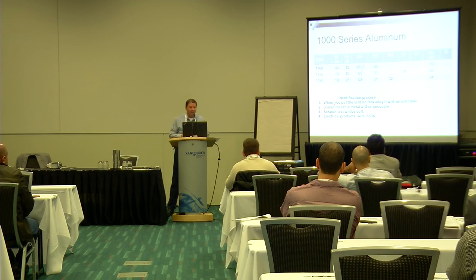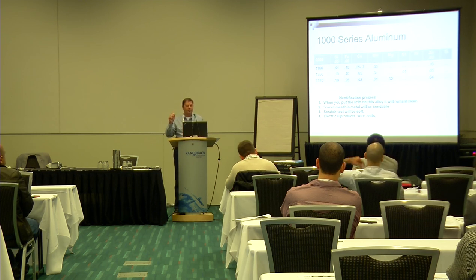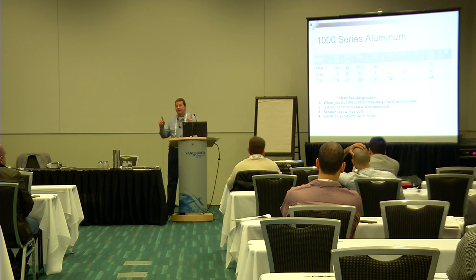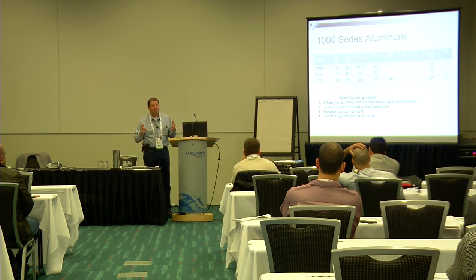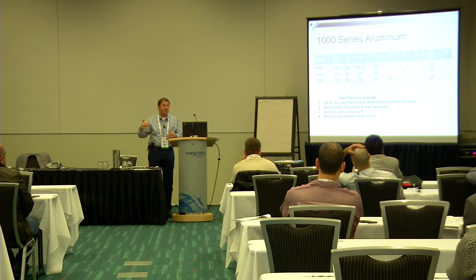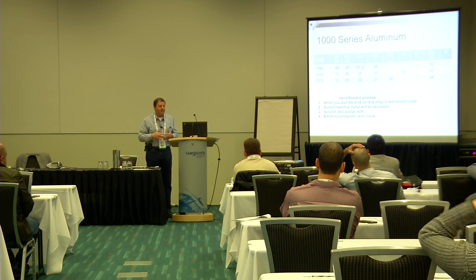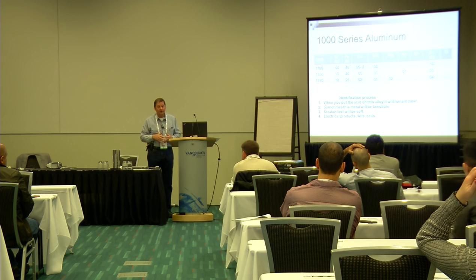Okay. Now, look at the next one down, the 1350. Look at how it can change. The silicon, 0.1. The iron, 0.4. Copper, 0.05. And we're talking about very small traces of other things besides aluminum. And chrome, 0.01. Zinc, 0.05. 1350 is EC wire. Your EC wire is generally 1350 alloy. So if you're going to sell your EC wire to a secondary, you're going to want to say, hey, look, this is EC wire, and you're going to want to have a premium for it because it's so good.